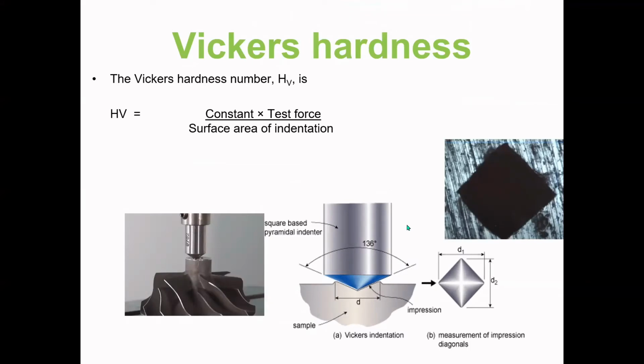Okay, now we move on to the Vickers hardness testing method, also referred to as the micro hardness testing method. The micro hardness test method is mostly used for small parts, thin sections, or case depth work. This method is based on an optical measurement system. The micro hardness test procedure, like what we have in ASTM, American Society for Testing and Materials, E384, specifies a range of light loads using a diamond indenter, like what we have in the figure here, to make an indentation which is measured and converted to a hardness value.